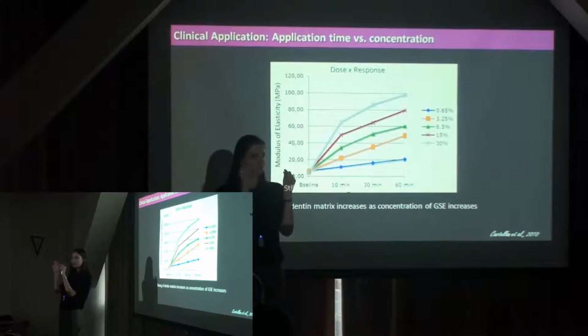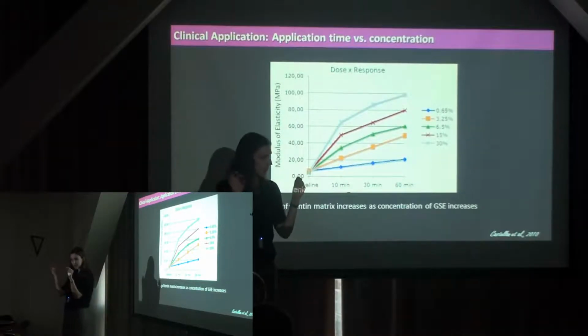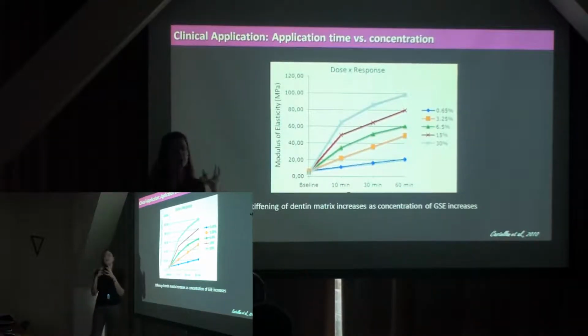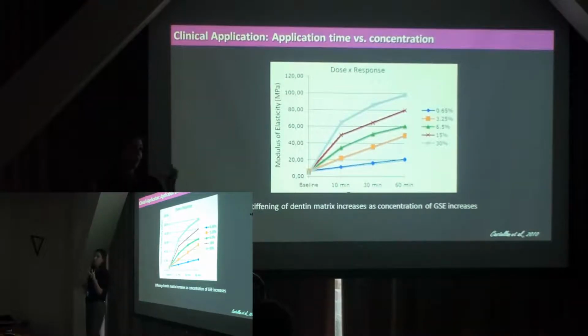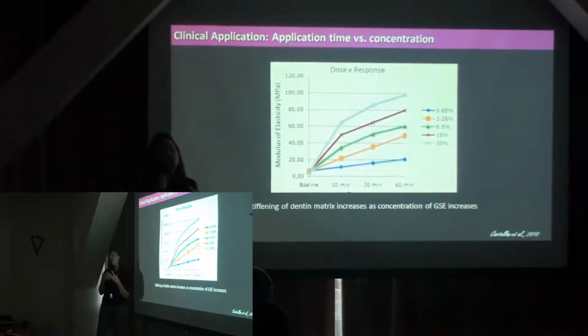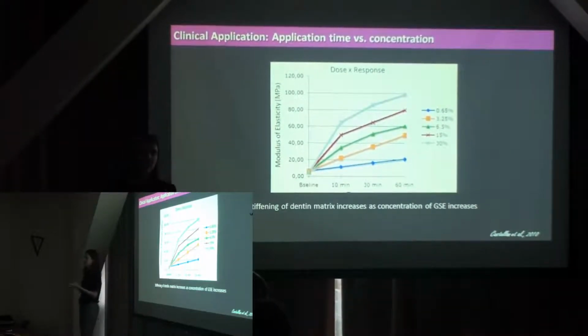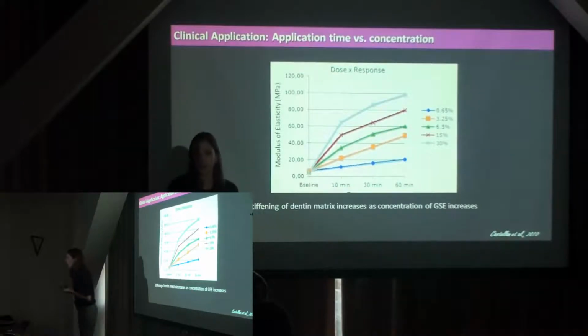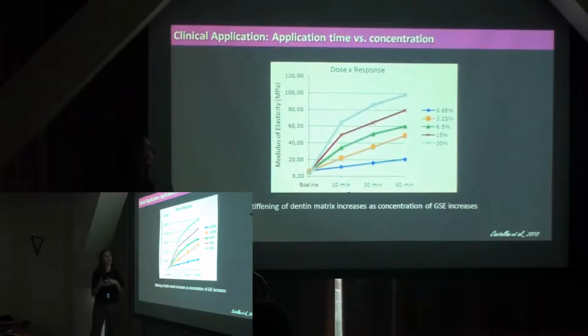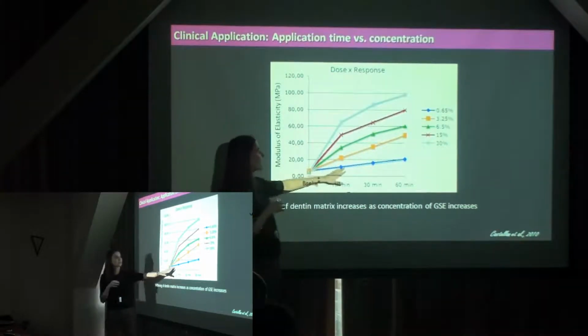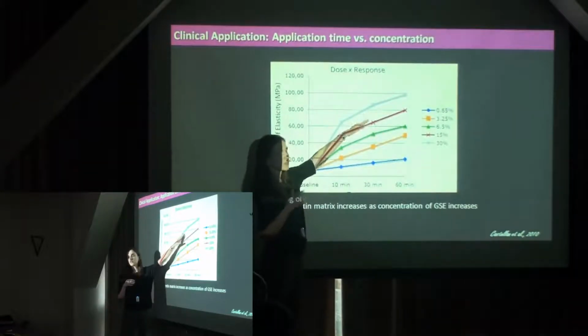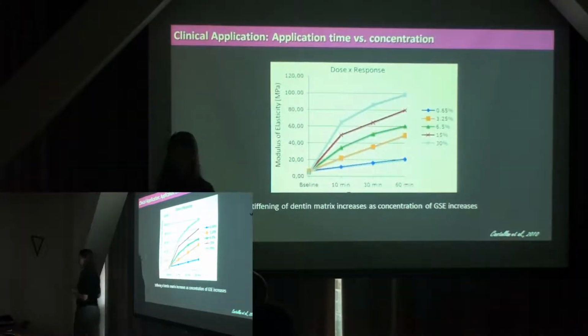We're talking about a 4 or 5 micron surface that we play with, but when we started doing these microtests, we're looking at 500 micron thick samples, so we're using about an hour to get some results. So we start doing our test using 1-hour treatment, and that's not feasible clinically at all. So we start having to look at concentration-dependent effect.